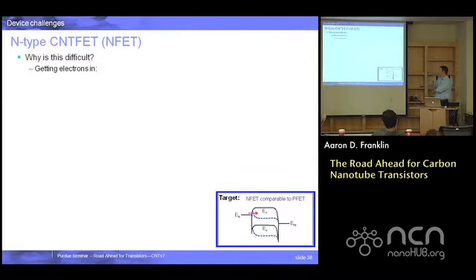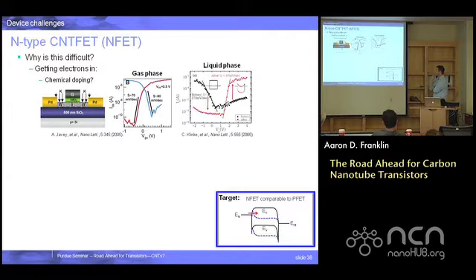So where we are, well, there's been some good progress made in the years. It started with some one-off demonstrations where people would do some type of a dopant, not substitutional or interstitial the way that you may think about it with silicon, but a dopant where, when put in the vicinity of a nanotube, it creates a charge fluctuation or a permanent sort of charge shift, like an electrostatic movement of the band structure, and that way effectively dopes the nanotube. These are some examples of that. There's problems with this type of chemical doping. One is in terms of reproducibility, consistency across the substrate, and robustness to air, especially these earlier ones where they use potassium. The devices turned out well, but these sort of things have issues in the manufacturing sense.